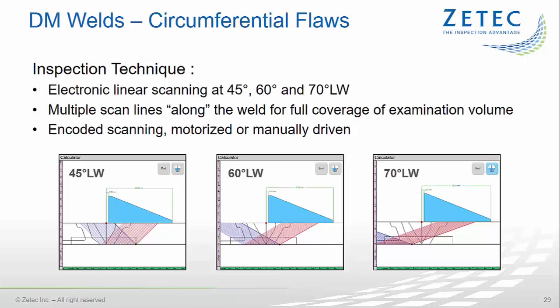As shown before, the Ultravision Touch advanced software allows the operator to simply select the required dual array probes and wedges from the database. The onboard calculator then allows to define the appropriate parameters of the focal law groups for linear scanning and gives direct visual feedback on the coverage provided by the three insonification angles as shown on the images of this slide. The ultrasonic beams are oriented perpendicular to the weld, and a multiple line inspection sequence is used to fully cover the examination volume.